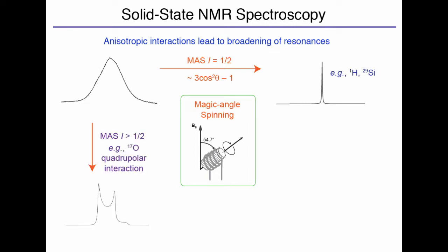We can also do this for spin greater than 1/2, which are known as quadrupolar nuclei. And unfortunately, this is the area I work in. Nothing is ever simple. So we can still do this magic angle spinning, and it reduces those line widths, which is good. But in many cases, it's still difficult to find precisely how many lithium sites you have, sodium sites, the number of environments that you're actually looking at.